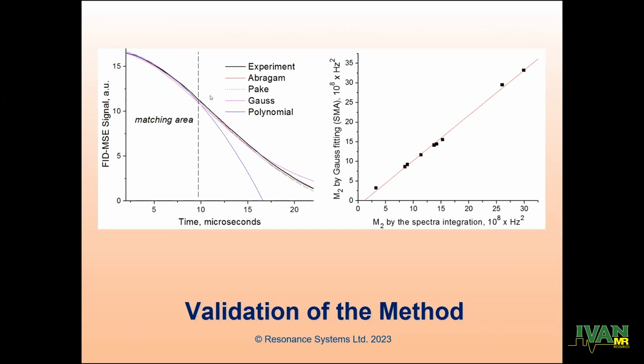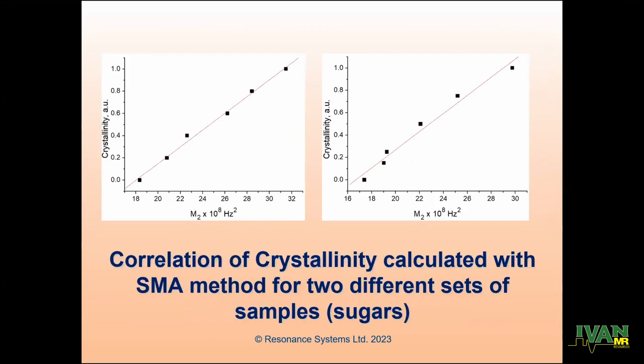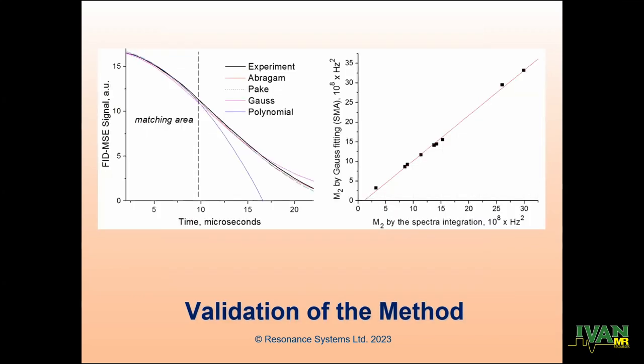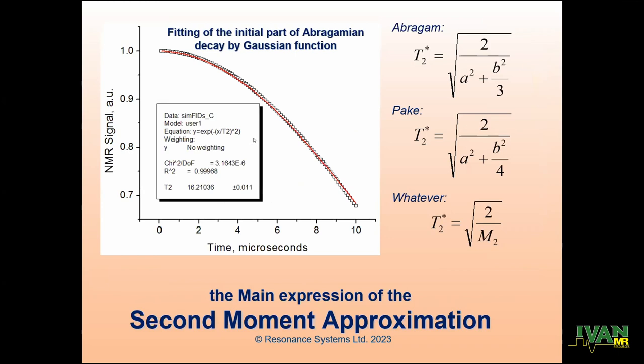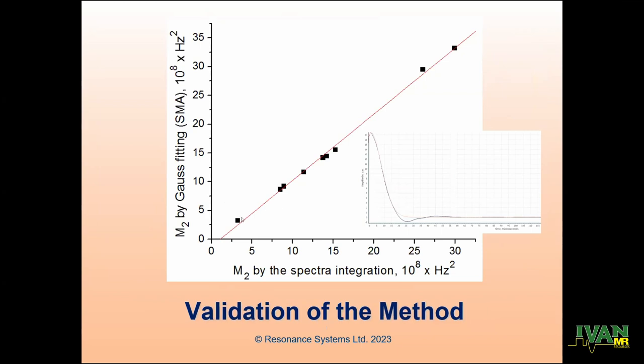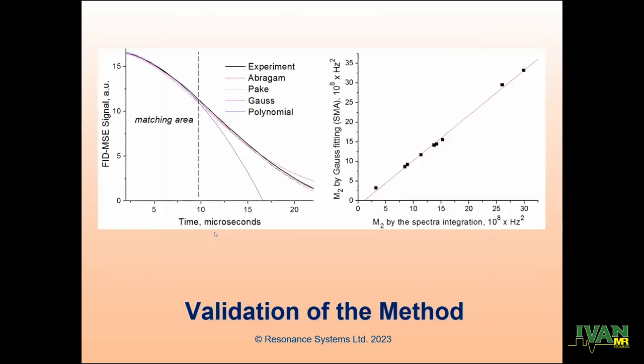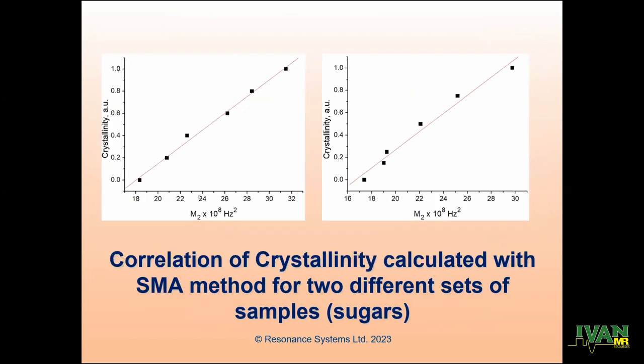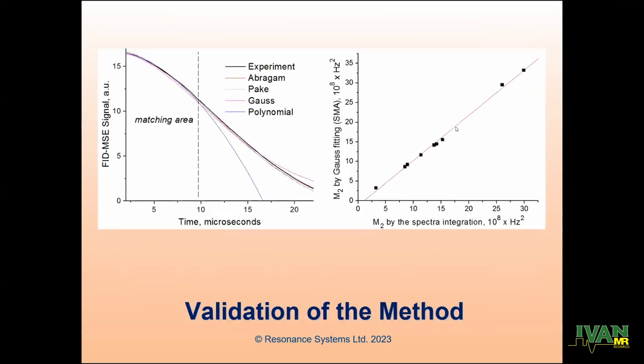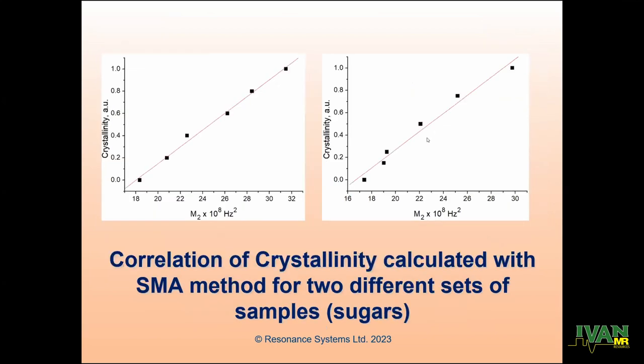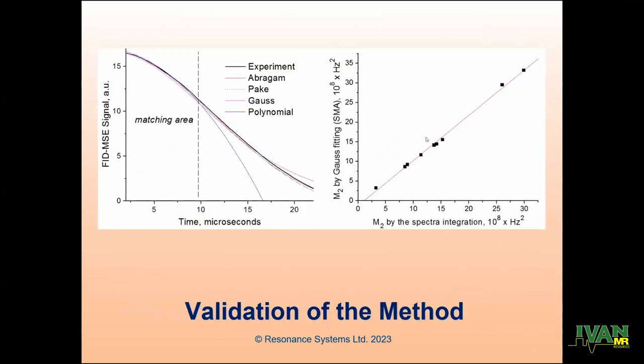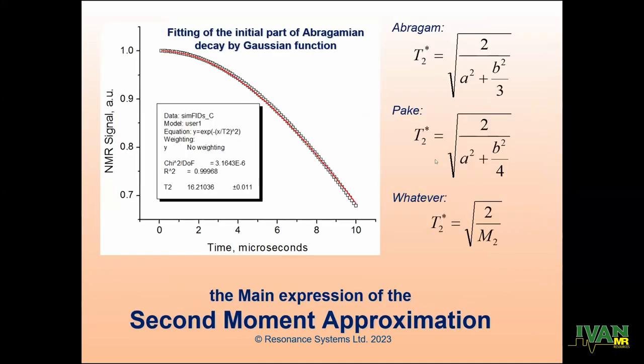It means that this approach of the so-called second moment approximation, what we are doing, is very much interesting. So we can fit with the Gaussian the beginning of any relaxation curve, and this will work. This will give you a correlation, for example, with the crystallinity of sugars, of anything. So just take the second moment and then you can convert this second moment into the relaxation time using such an expression.